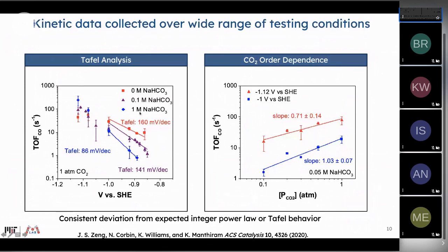If we look at the CO2 order dependence, we see a slope which ranges from 0.7 to 1.03, depending on the potential. At a lower overpotential, -1 volt versus SHE, we see an approximate first order dependence. But if we go to a higher overpotential, the CO2 order dependence drops. So these are a set of observations which one could not explain through simple linearization of the data.